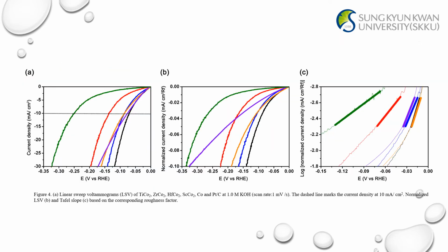Well, the next page is an electrochemical test. We can see in the figure that our materials have extremely excellent hydrogen evolution performance under alkaline conditions, even better than that of platinum metal. It strongly confirms the conjecture we made before.